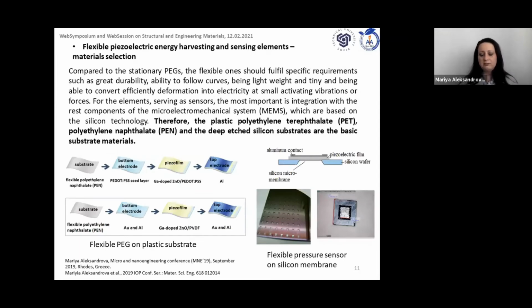So in our studies, we used plastic substrates from polyethylene naphthalate and polyethylene terephthalate as a flexible substrate for the harvesting technology. And for the sensing technology, we used deep anisotropic etched silicon substrate. In this way, this middle square part is converted from a solid silicon piece into a flexible silicon micromembrane that could be moved and deviated at supply pressure. And on top, we grow our piezoelectric films.